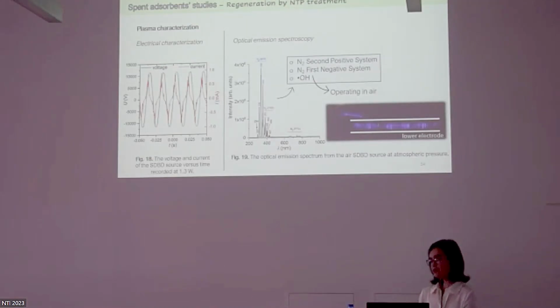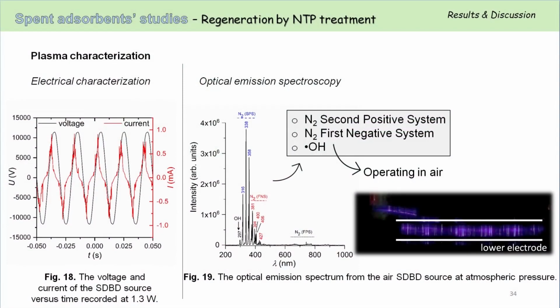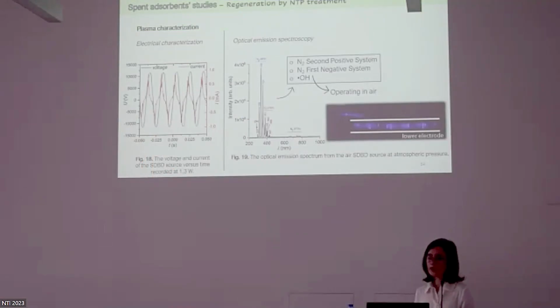Before I continue with the results of regeneration, first the plasma characterization was performed. The electrical measurement shows stable plasma during these 20 minutes of treatment time. To investigate the species present inside the plasma, optical emission spectroscopy was used. As expected for air plasma, the most intense lines in the spectrum were for the nitrogen second positive system, then the nitrogen first negative system, and there are also lines for OH radicals.